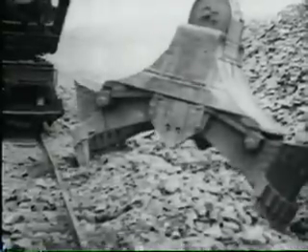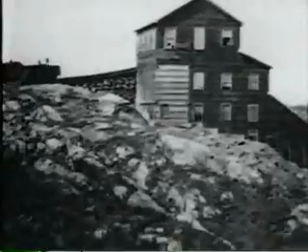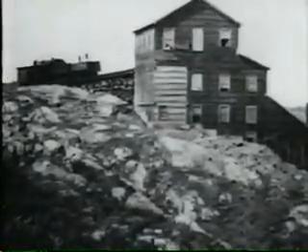Everything in 1915 was working full out to satisfy the wartime demand. One of the metallurgically most interesting advances in smelting technology employed at the Coniston smelter was flotation. In this process, the low-grade ore was first taken from the storage yard to the flotation mill. Ore which contained only about 15 or 20 pounds of nickel and copper sulphide per tonne had previously been rejected, but it was now enriched in the flotation mill.